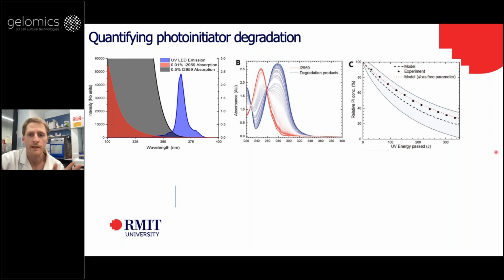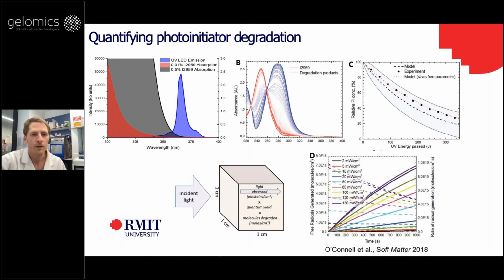Using this kind of approach, we can calculate properties such as the molar extinction coefficient, and knowing the absorbed energy which we get from the overlap in the first graph, we can also calculate the quantum efficiency, which is the proportion of molecules which when hit by a photon actually generate a radical. So this might all sound quite academic, but using these numbers, you can actually work out things like what is the free radical flux. That means how many radicals are being generated per volume per second at a particular light intensity or concentration. This analysis is all done without having any hydrogels involved just yet, just to understand the system.